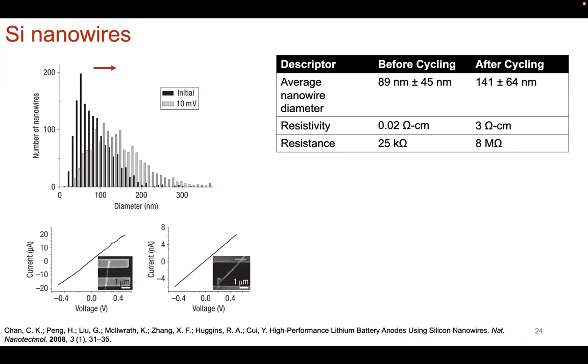Now, in terms of statistical representation, how many of these silicon nanowires were really investigated? Well, in terms of the count, the number of nanowires that were actually looked at is about a few hundred, so good enough. That's not 10, but it's not 2,000, so it's sufficient enough for us to try to understand what is happening in the system. Is this representative, or is this one fabulous nanowire that was created? And in terms of trying to understand also the phase transformation within these nanowires, we can also do just regular resistance measurements. Here it's not your typical 2-point probe. Well, it is, but at the MEMS device level type of device.